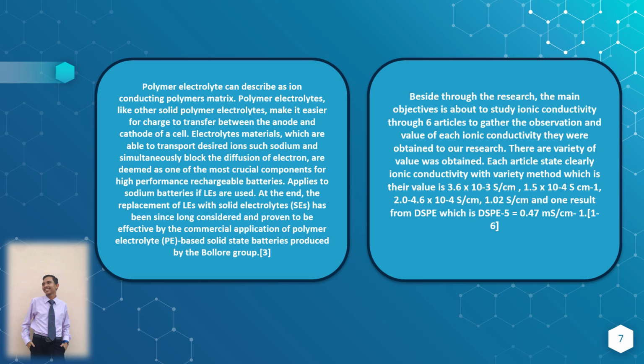Besides the research, their main objective is to study ionic conductivity through 6 articles to gather the observation and value of each ionic conductivity obtained in our research. There are varieties of values obtained. Each article states clearly the ionic conductivity with varying values: 3.6 times 10 to the power of negative 3 S per cm, 1.5 times 10 to the power of negative 4 S per cm, 2.0 to 4.6 times 10 to the power of negative 4 S per cm, 1.02 S per cm, and one result from the DSPE, which is DSPE-5 equal to 0.47 mS per cm.